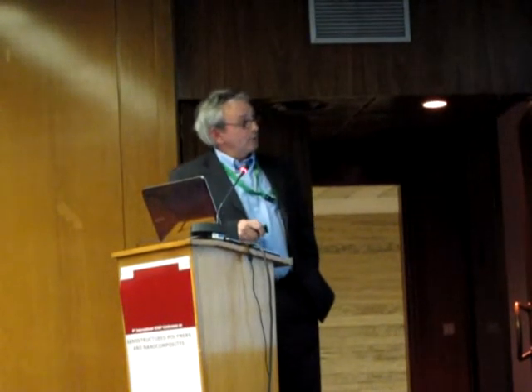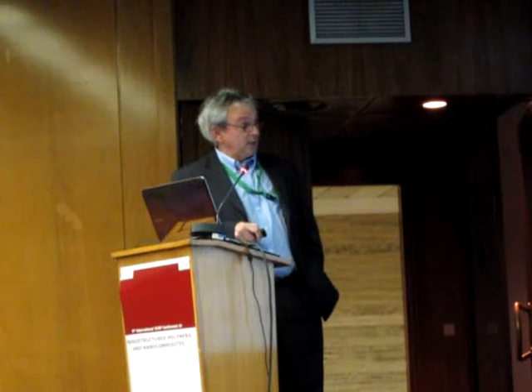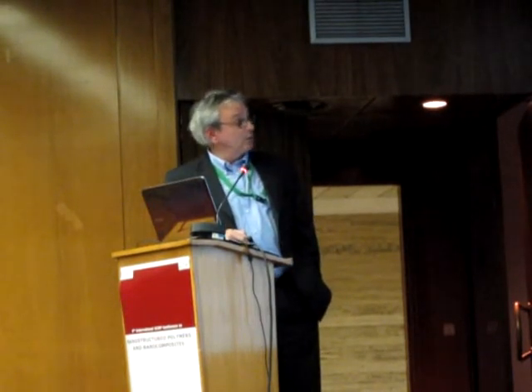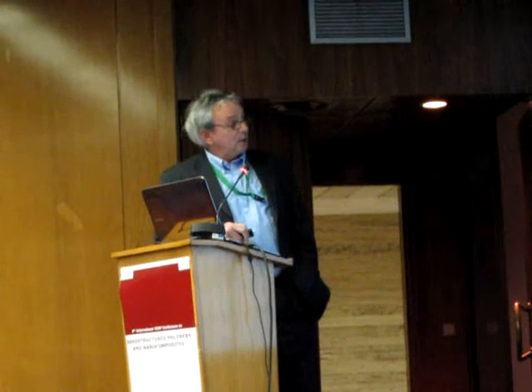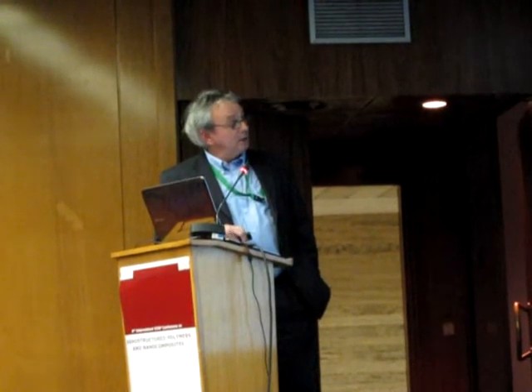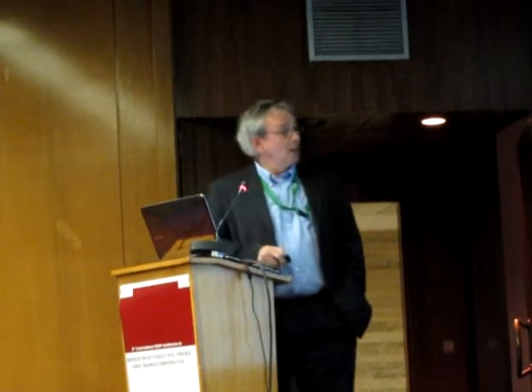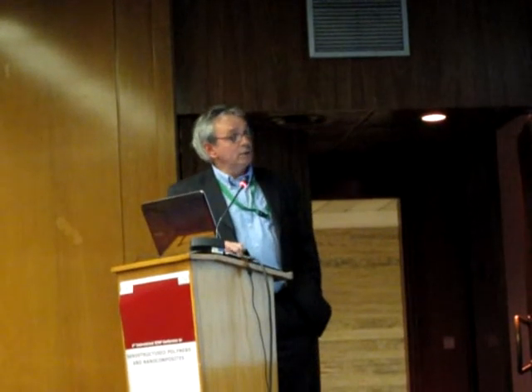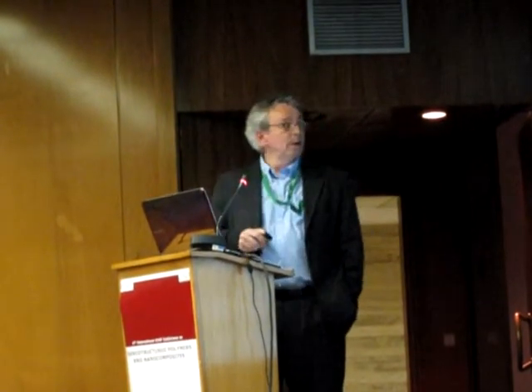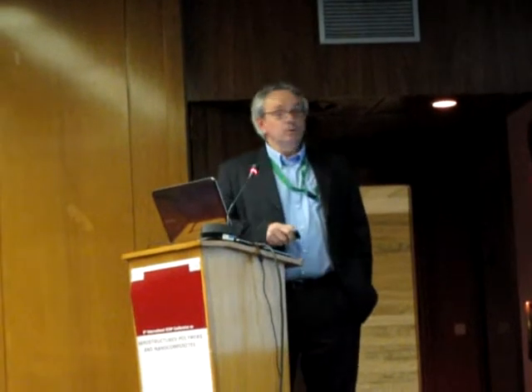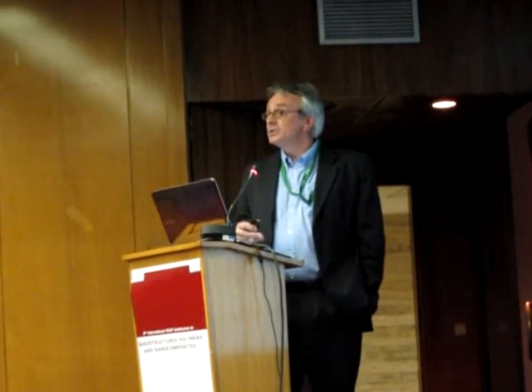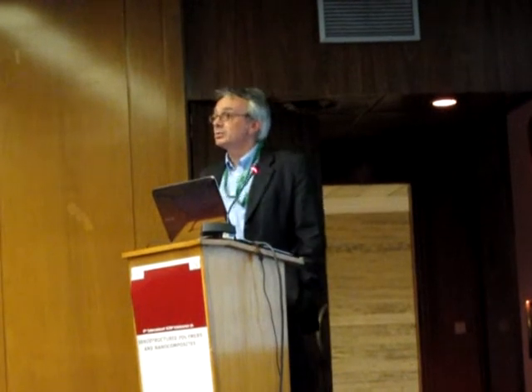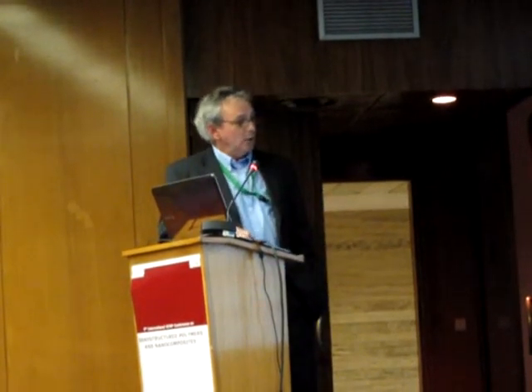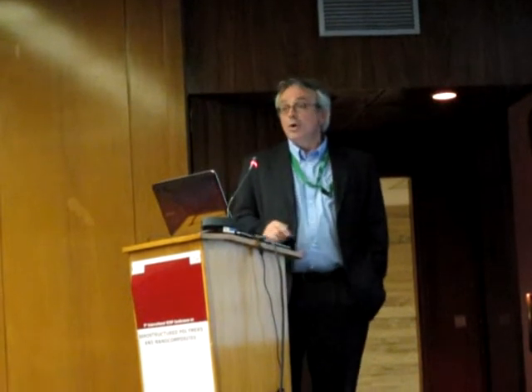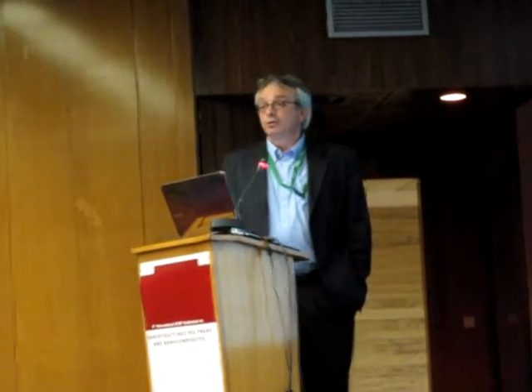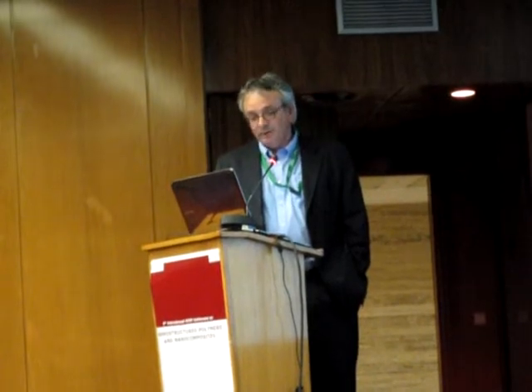And also surface functionalized silica, with 200 square meters per gram, modified with a methacrylate or modified with a hydroxy-terminated silane. This one will be interesting because we can expect some ring opening polymerization from the silica surface, in order to graft in situ, to make some grafting from in situ during the process. And we will go to a low amount of inorganic phase, of about 5% by weight.